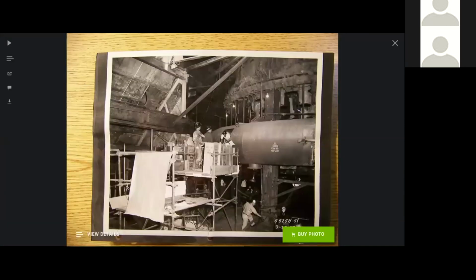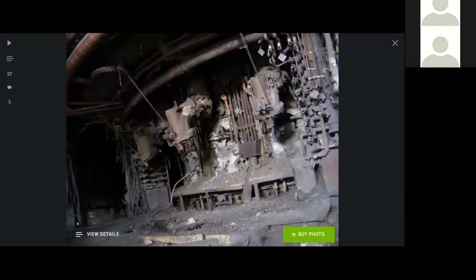Now, the actual furnace itself got its air from, again, this term comes from women's clothing, the bustle pipe. This encircled the furnace. These guys are inside trying to put a refractory brick lining because, again, everything here is tremendously, tremendously hot. And then from this bustle pipe, which encircles the furnace, these goosenecks hang down, and they are connected to these copper-made water-cooled tuyeres, which are basically pipes that allow the air to flow from the bustle pipe above through these goose legs and goosenecks and through these tuyere pipes into the furnace itself, and that's how the hot air gets in there.